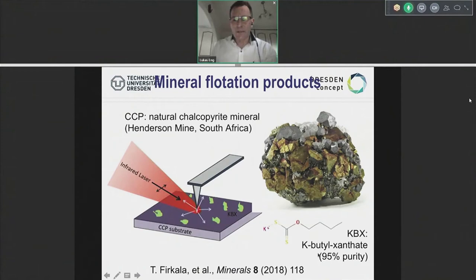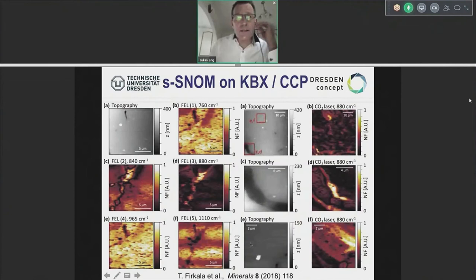And we did the same experiment as shown before, testing it with different wavelengths. Going through different wavelengths here, by using the CO2 laser, it gives us a bright contrast at 880 inverse centimeters, which is infrared, and which tells us these molecules stick preferentially to these areas. So we could interpret that in a very nice paper, that this is the preferential adsorption site for these molecules.